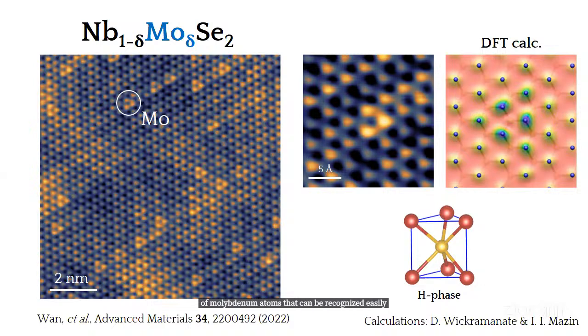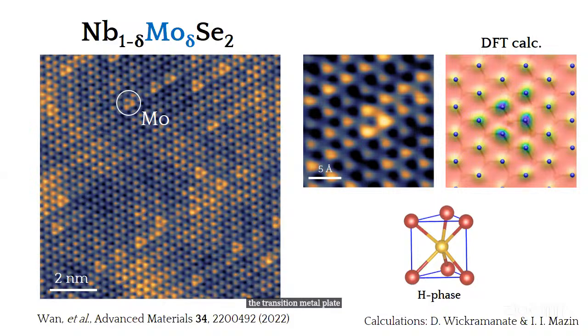So do you see these triangular features here? You can basically count them. Each of those triangles represents a molybdenum atom. The reason we see it is that the presence of a molybdenum atom changes a little bit the density of states of these upper and lower atoms. We don't see the transition metal plane, but we see the selenium planes, and they are a little bit different, and can be counted one by one.